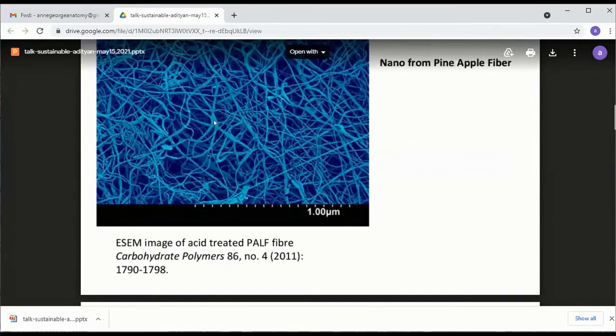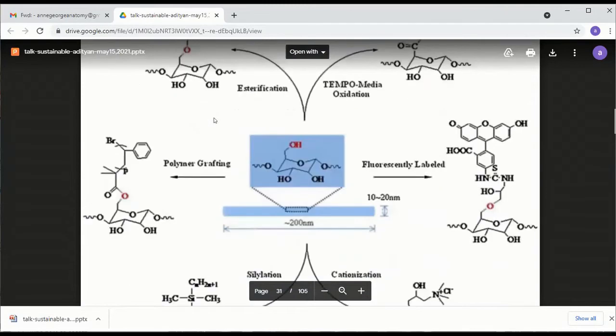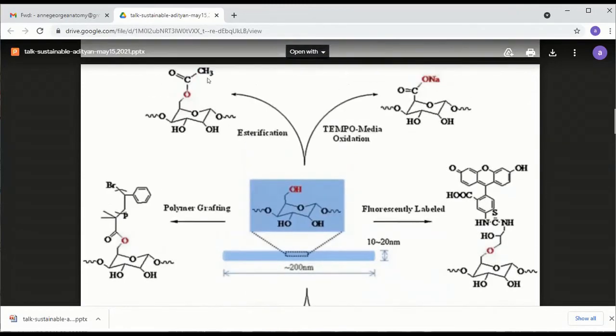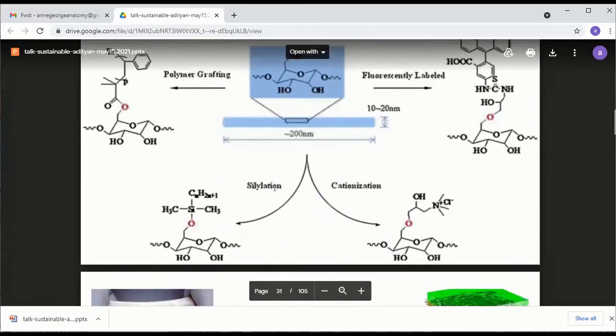Now let me show you another important slide. This slide is very important for chemists. You see, nanocellulose has beautiful hydroxyl groups. If you're a chemist, you can do several reactions from the surface because these reactions are very important to make a strong interface. You can do TEMPO oxidation process. The OH could be converted into COOH. You can do esterification reaction. You can do polymer grafting. You can put fluorescent labels on the surface of nanocellulose. You can do wonderful fluorescence spectroscopy work. You can do silylation reaction.